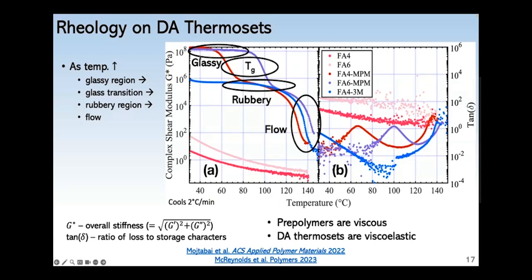So if we start at low temperature, the materials are initially glassy and very stiff. They undergo a step change in their softness, going through the glass transition and become more rubbery. And then at high enough temperature, after enough RDA reactions occur, they completely degel and flow. And so just here, you can see that the DA polymers have a clear viscoelastic character compared to the prepolymers down here, which show just viscous character.